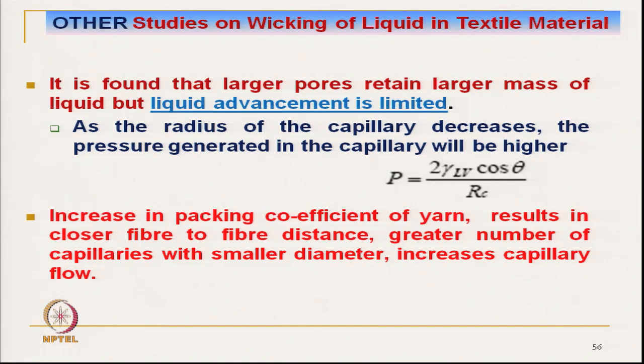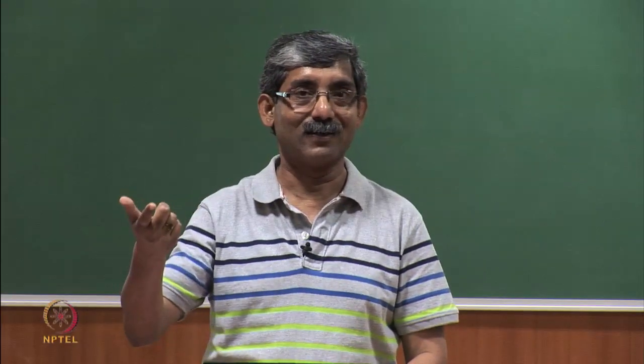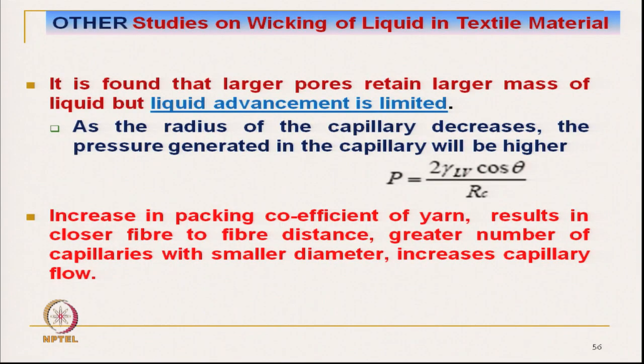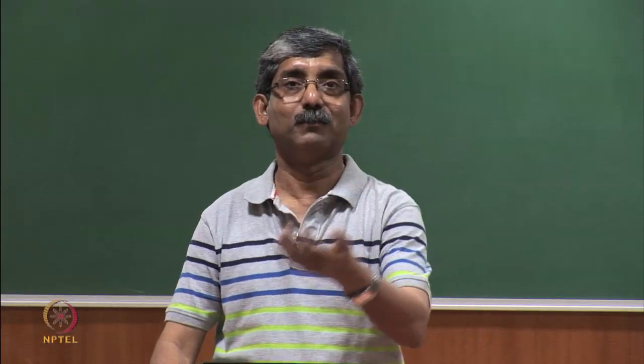Increase in packing coefficient of yarn. If we increase the packing coefficient, it means the filaments or fibers are coming closer, so the Rc, which is the pore radius, will be low. This results in closer fiber-to-fiber distance, and a greater number of capillaries for the same yarn, with smaller capillary diameter, which will increase the capillary flow. So, a larger pore in smaller number versus smaller pores in larger number: the second one is better for liquid transmission through the capillary.